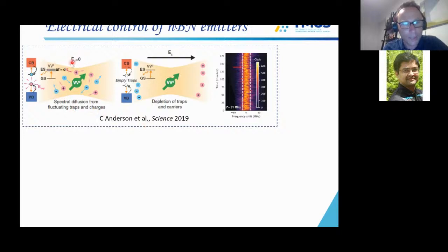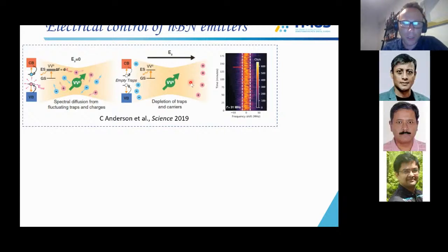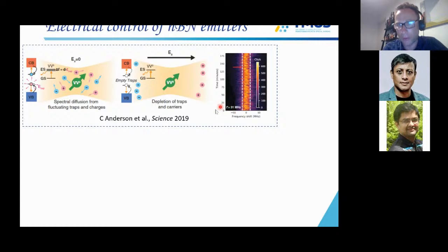And what they saw in silicon carbide is that if you're just doing photoluminescence excitation, so resonant excitation, under zero field, you have all these charge states. And of course, we see the same thing in hBN. But when you apply a bias and you create a depletion level and you really get rid of all the charges around the defect, you can see a very narrow and beautiful line of about 31 megahertz.